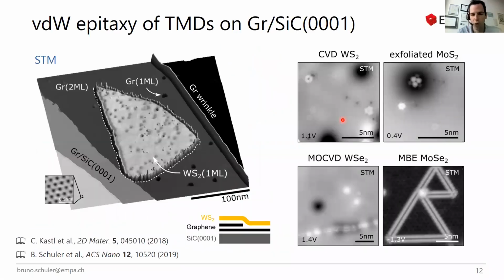So that's kind of an overview STM image of how a typical sample may look like. That's tungsten disulfide, one flake of tungsten disulfide. That's a rather small island here, grown on graphene on silicon carbide by CVD. And we were very lucky to have good collaborators that grow these samples for us. Especially I want to highlight the groups of Josh Robinson and Mauricio Terrones from Penn State, and Christoph Kastl and Alex Holleitner from the TU Munich, that are really excellent collaborators that help us grow in a targeted way these kind of TMD samples.